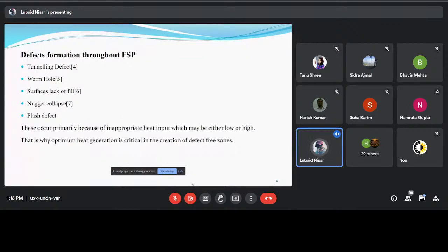The first is the tunneling defect. This is one of the most common defects that arise due to less heat input, which results in inadequate plasticization of material and improper material movement around the pin. In this case, the tool penetrates further, resulting in less deposition of material in the gap left behind it, making a tunnel. That is why it is called a tunneling defect.